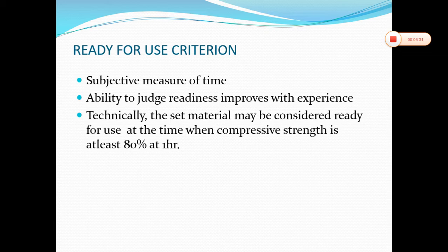Technically, the set material may be considered ready for use at the time when compressive strength is at least 80%. So by the final setting time, the strength has to be 80% minimum. It is achieved by about 1 hour. So the material is ready to use by about 1 hour.